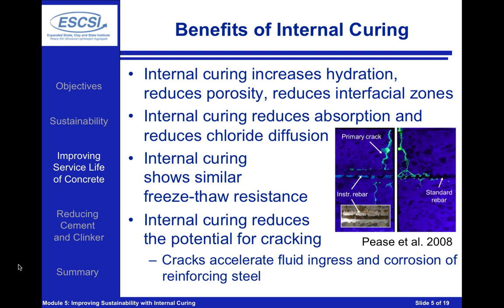When we discuss transport properties, we're really discussing how the concrete absorbs water or absorbs solutions that contain chloride ions or other ionic species, or how these ionic species diffuse through the concrete and get toward the reinforcing bar. So internal curing, by hydrating more of the cement, reducing the porosity and reducing the connectedness of the interfacial transition zones, is going to reduce the speed at which the chloride ions can get to the reinforcing bar. By reducing that speed that the ions are going to move through our concrete, we can extend the time that our concrete will be in service before the corrosion starts at the bar.